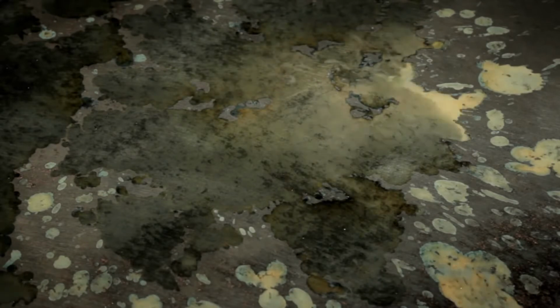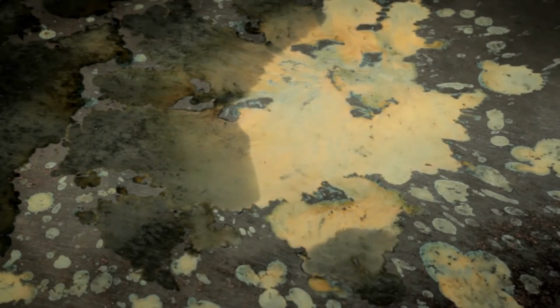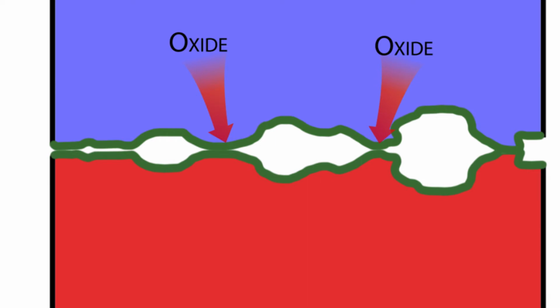The same thing happens with aluminum, but in the case of iron, the rust keeps falling off and eventually the part will rust to nothing. Aluminum has a benefit in that the aluminum reacts with the oxygen and creates a protective coating that limits the oxidation from eating the aluminum. The problem is that layer is an insulating layer. So if that layer is not removed prior to making a connection, you actually have an insulative layer inside your connector. So it's important that when you're making your connection you remove that oxidation layer prior to installation.